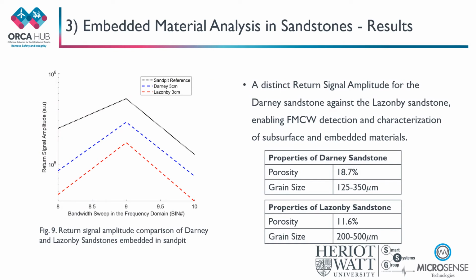Figure 9 displays the return signal amplitude of the sandpit baseline reference, Darney sandstone and Lazonby sandstone, once again focusing on bin 9 due to the main reflection from the interface of the sandstone. First, it is important to understand the properties of Darney and Lazonby sandstone. Darney has a porosity of 18.7% and contains relatively well-sorted subangular quartz silicon dioxide grains of fine to medium grain size of approximately 125 to 350 micrometers, with subsidiary orthoclase feldspar and clay present within some of the pore spaces.